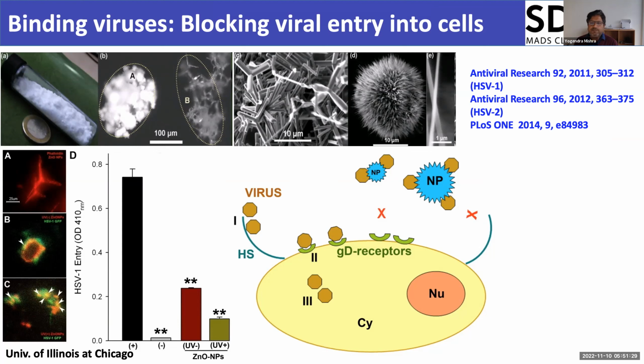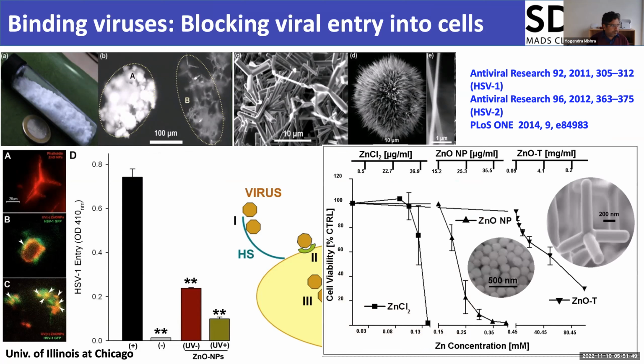To validate it, we studied herpes simplex virus type 2, the genital herpes virus, human papilloma virus, adenovirus, and many different kinds of viruses. Our motivation kept increasing that we could probably go to a much higher level. But one question we should ask ourselves when working with nanoscale material is cytotoxicity, because if our material is cytotoxic, then it is not going to be helpful. So we did a detailed cytotoxicity study, and we found that zinc oxide is much less cytotoxic in tetrapod form as compared to nanoparticles and zinc chloride. That motivated us quite a lot to go further.